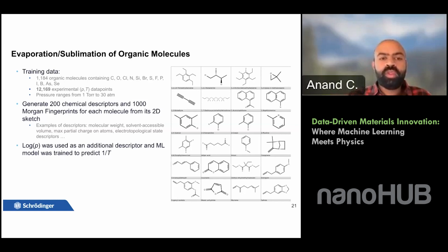So we took this data set from literature. We scanned through the literature, and we had more than 200 chemical descriptors and 1,000 Morgan fingerprints for each molecule, so more than 1,200 descriptors. We also provided the logarithm of pressure as an additional descriptor to the machine learning model, because we know that there's a linear relationship between the logarithm of pressure and the inverse of temperature because of the Clausius-Clapeyron rule. So we want to provide this physics-based intuition to the machine learning model.